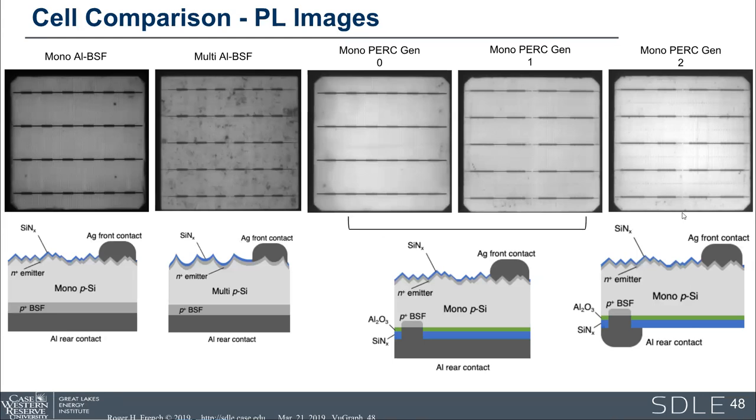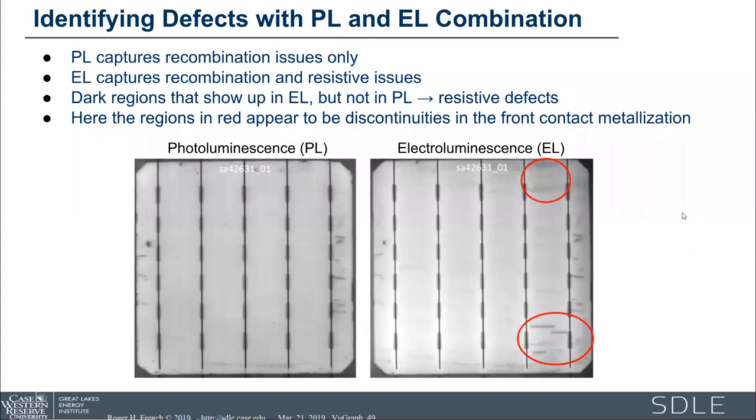Next slide. So what we can do with some of the PL is compare it with things like the EL imaging, which is very common to do for modules, and we can start to pick up interesting types of defects. So PL really just captures the recombination issues when we're doing open circuit PL. We're doing it open circuit, so it doesn't capture any of the resistive losses, whereas EL captures both recombination